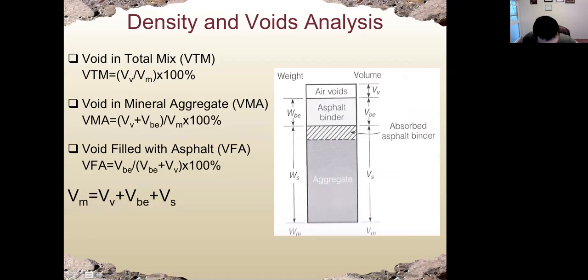All right, so now the next couple of slides, let's talk about small calculation problems. This is how we calculate the density and voids for asphalt concrete. Let's look at the picture on the right. So here shows what is inside asphalt concrete. We have aggregate, which is here. The majority of the volume is occupied by aggregate. And we also have asphalt binder, which has two parts. One part is called absorptive asphalt binder, which is the asphalt absorbed on the surface of aggregate.